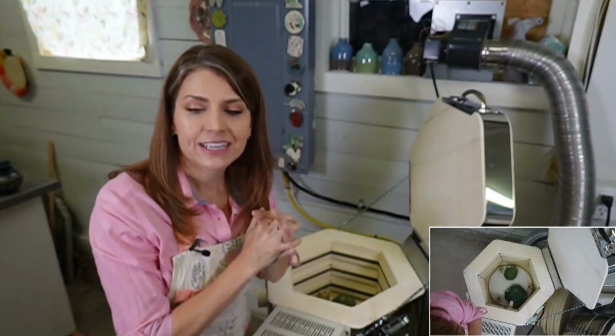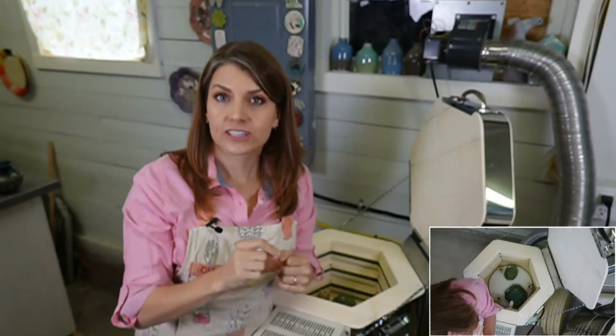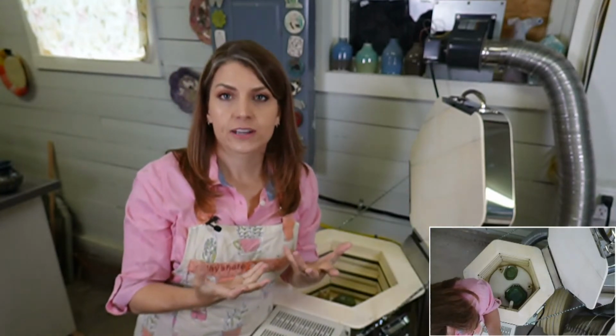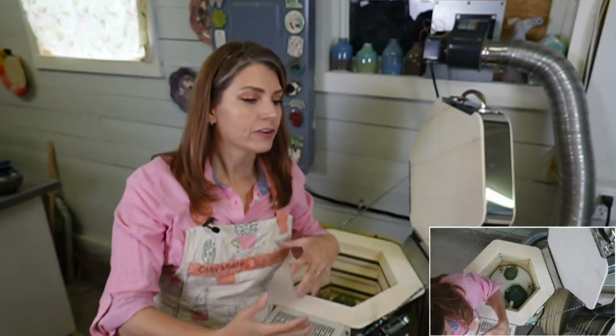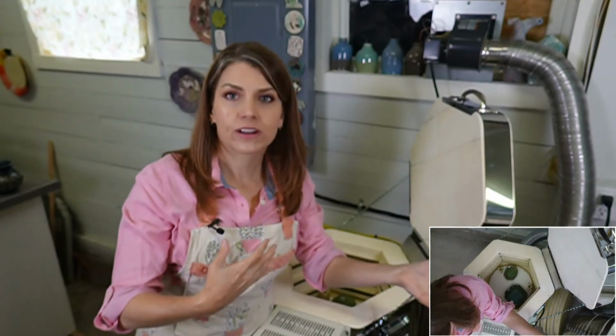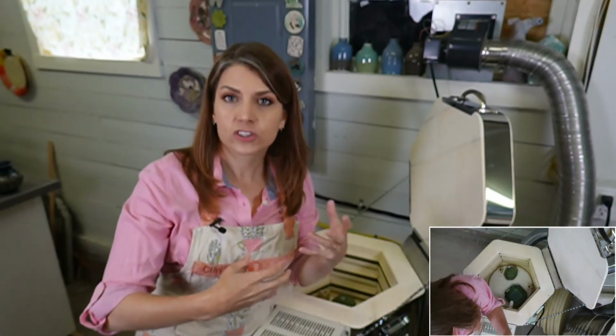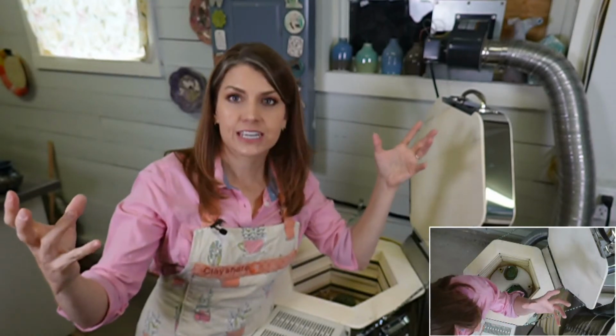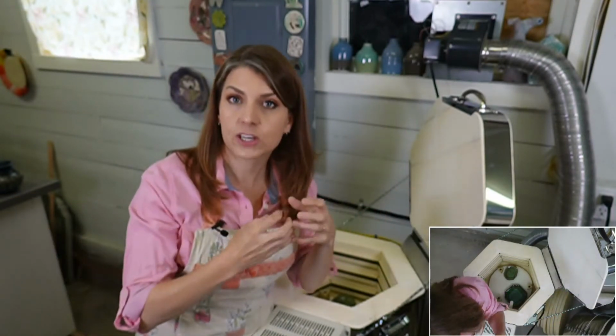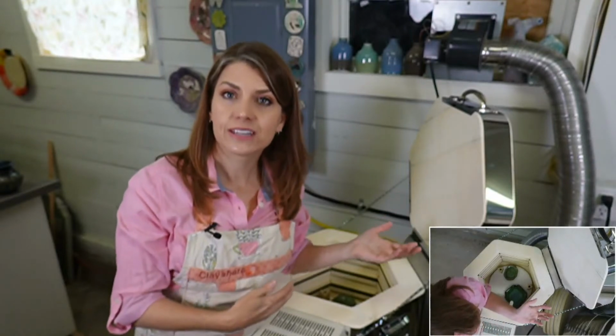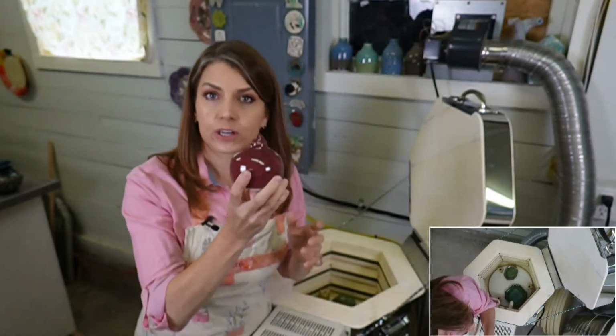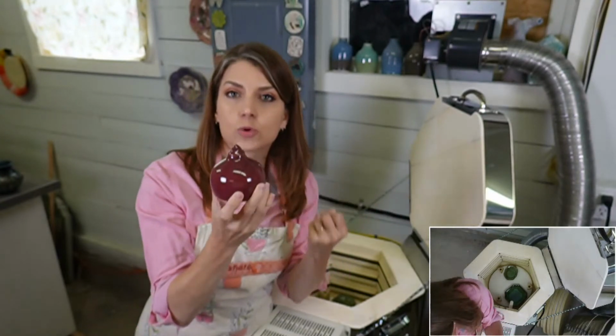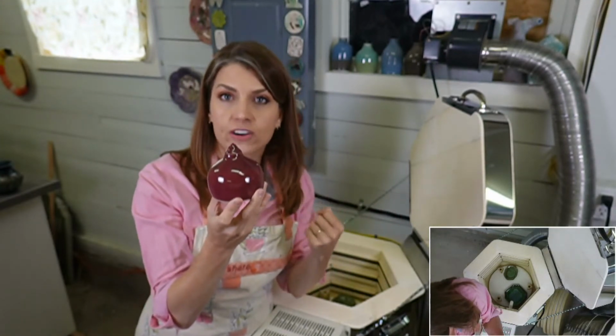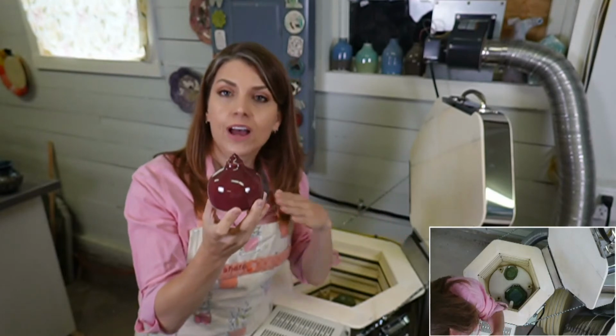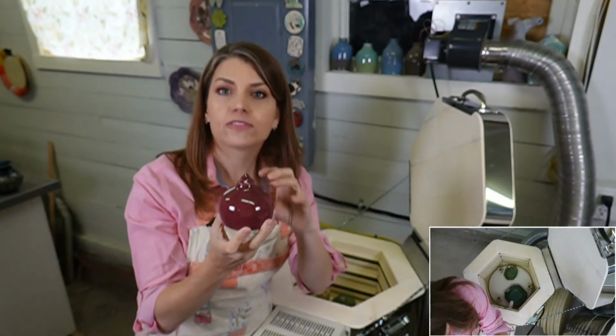So why do I preheat my glaze fire for an hour and a half? That's a really good question. We have two types of water that we're trying to burn off our pottery. We have chemical and physical water. When we're doing our first fire, our bisque fire, we want to do a nice long preheat because the physical water is coming off as steam. And if you go too fast, that can erupt and actually make your pottery blow apart. Similar thing when we're doing glaze firing. You have dipped your piece or brushed your piece in a glaze, so the clay has absorbed water. So you have physical water in there, and still there's chemical water too. So I do that hour and a half preheat to help burn off the physical water.